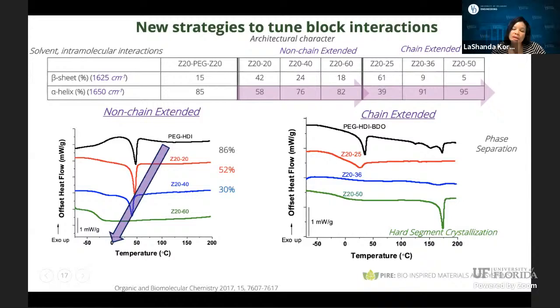So this indicates that there is some phase mixing, most likely with the lysine with the hard domain, so the HDI hard domain. For the Z2036, you can start to see the emergence of your hard segment crystallization peak, but you now have an absence of your PEG transition peak, which means that you have more phase mixing within the soft phase than you have between the soft and the hard phase.